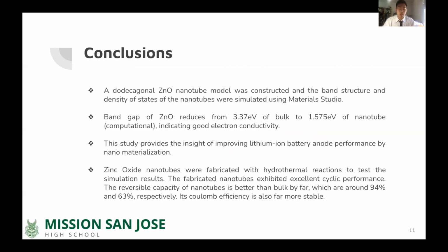So in conclusion, in our experiment, a zinc oxide nanotube model was constructed and the band structure and density of states of the nanotube were simulated using the model. The simulation results had a very small band gap, indicating good electron conductivity, inspiring the nanotube experiment. Zinc oxide nanotubes were fabricated with hydrothermal reactions to test the simulation results. The fabricated nanotubes exhibited excellent cyclic performance. The reversible capacity of nanotubes is better than bulk by far, which are around 94% and 63% respectively. The Coulomb efficiency is also far more stable.